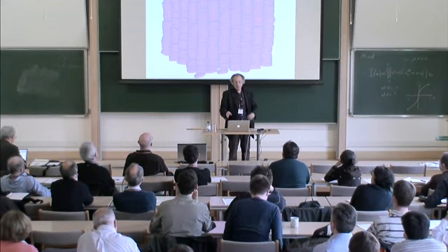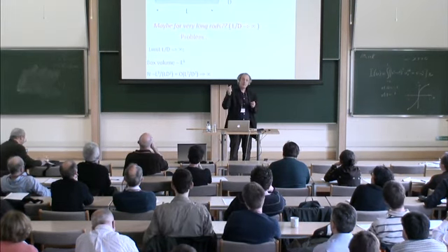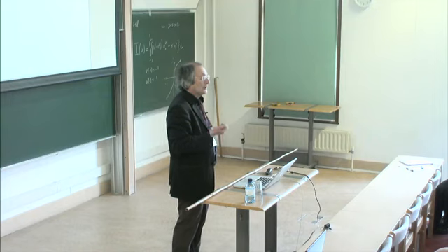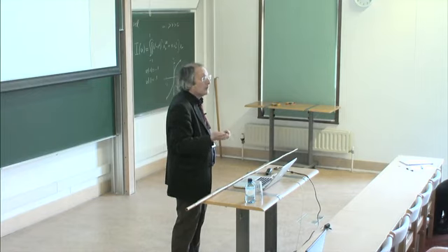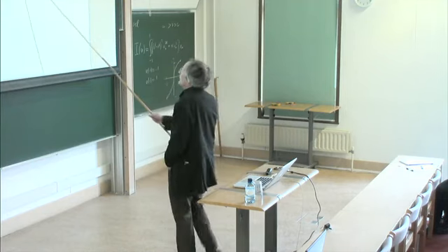The thing is that we know from the simulations of rod-like particles that for small aspect ratios, below 3.5 or 3.6, you don't get a nematic-smectic transition at all. At some point, if they're a bit like this piece of chalk, they start to form nematic and smectic phases, and then the simulations say up to an aspect ratio of about 100, we always see nematic and smectic. But we don't know a priori whether that's still true if you go to very, very long rods. So what would happen if you take the aspect ratio going to infinity?